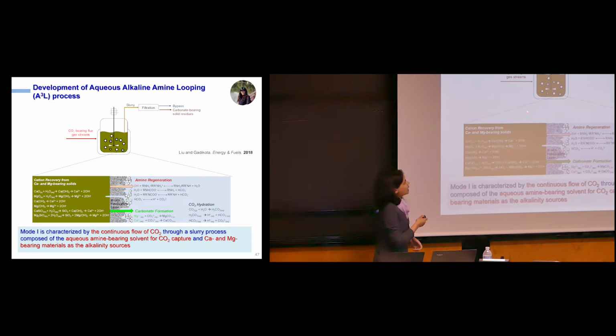So we want to design the chemistry of our aqueous environments. So we have basically an amine solvent, if you like. And what the amine solvent does is it actually captures the CO2 that may be present in the flue gas, converts that into a carbamate. And then what we want to do is we want this carbamate or bicarbonate to react with the dissolved calcium or magnesium. So we can form the magnesium or calcium carbonate and regenerate the amine in the process.